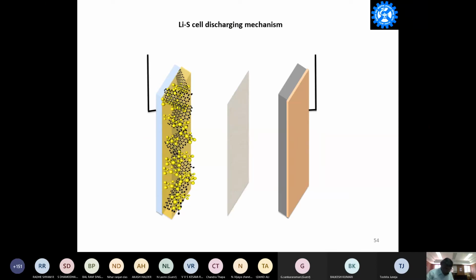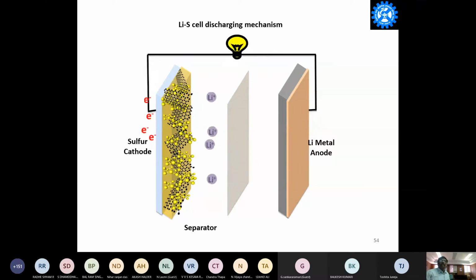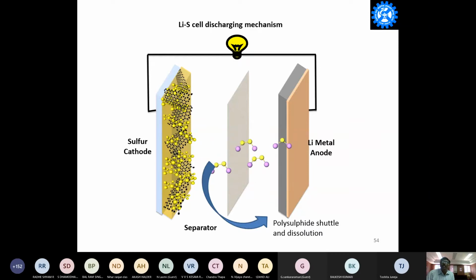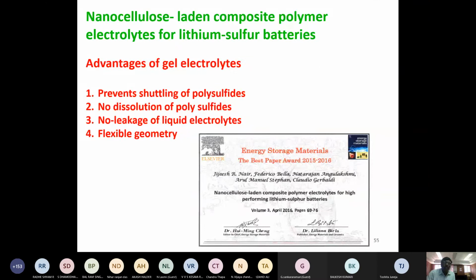So at first we have introduced a solid polymer electrolyte. Now I would like you to recall, when you charge and discharge, the lithium ions are migrating from the cathode to anode. But in this case, the lithium polysulfides are migrating. So if you put a suitable material instead of the porous material, you can simply prevent the polysulfide migration. So what we have done is, we have simply replaced the non-aqueous electrolyte with a gel electrolyte. This gel electrolyte has several advantages, because it not only prevents the shuttling of the polysulfides, there is no dissolution of polysulfides because there is no solvent, because this is solid. The second one is no leakage of electrolyte. And the third one is flexible geometry. It can be bent because there is no liquid. So these are the main advantages of the solid polymer electrolytes for lithium sulfur batteries.